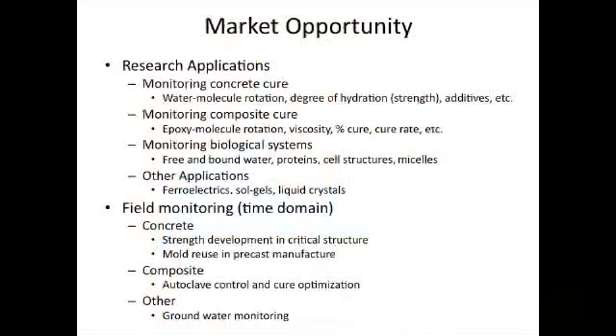For field monitoring we use a very simplified form of TDR — this little box — for monitoring strength development in concrete. We've done some plant testing there. Obviously if you're putting the first floor in on the Freedom Tower in New York, you want to know the critical strength is what it needs to be. We've also done field testing on monitoring precast development in the plant so the operator knows when they can take the molds off and reuse them, which is a time saver.